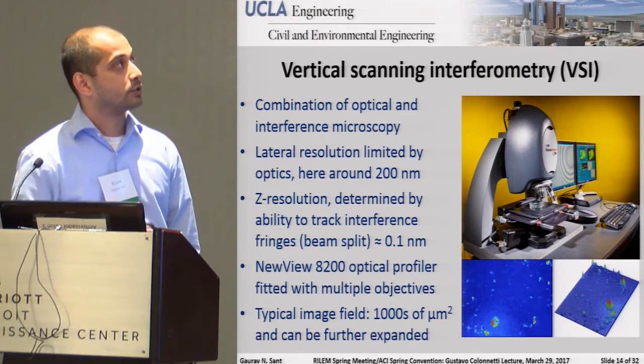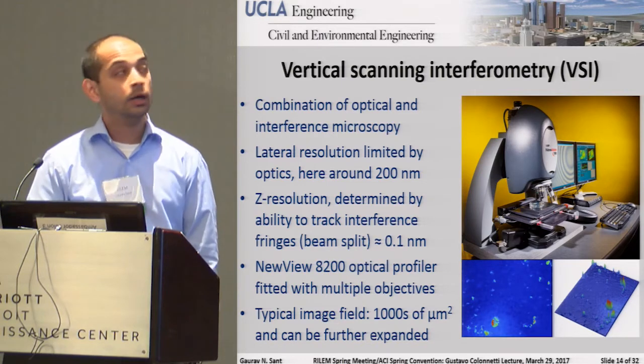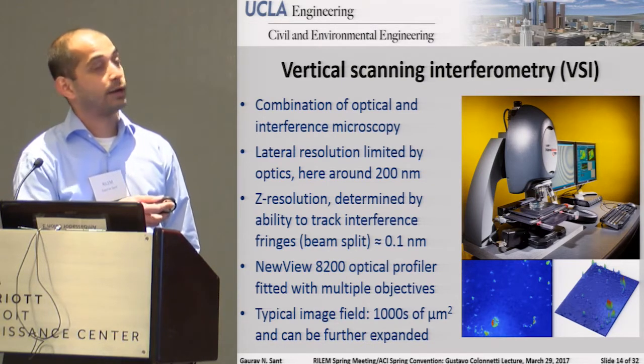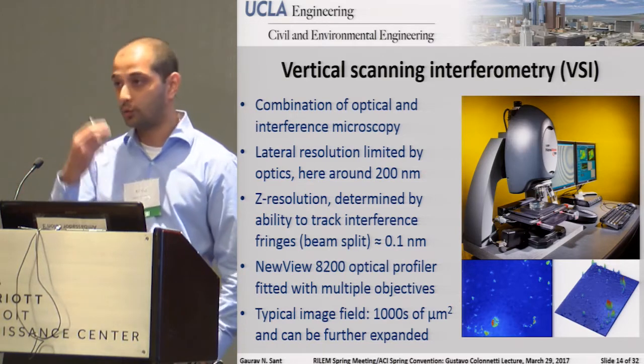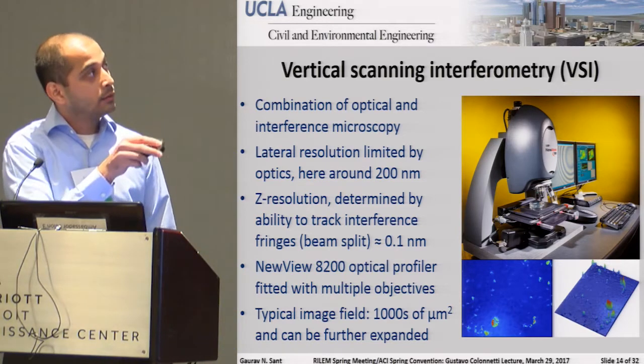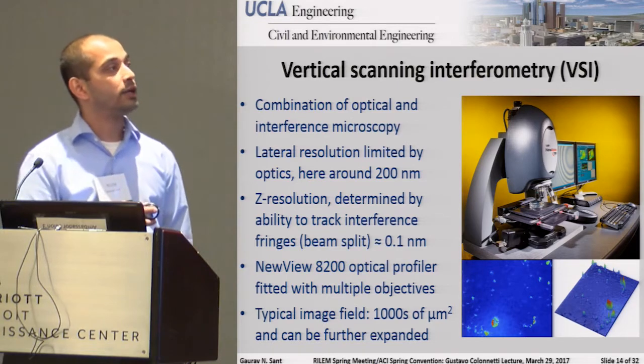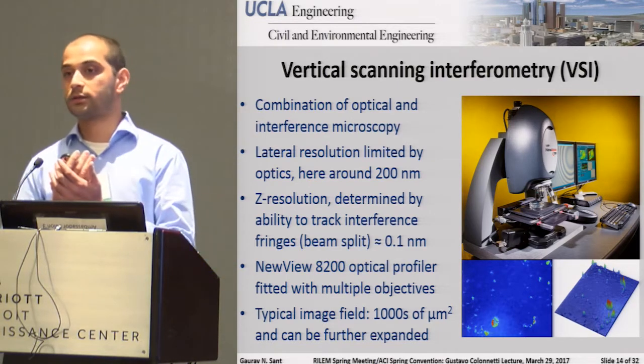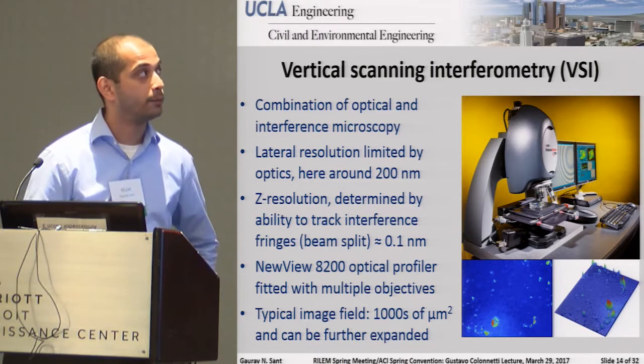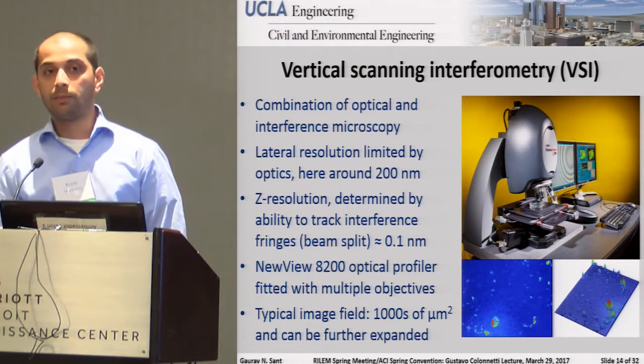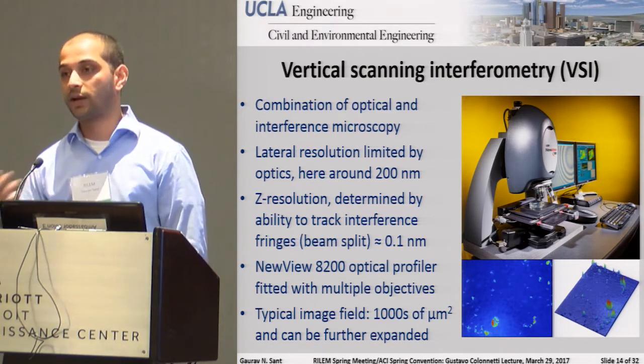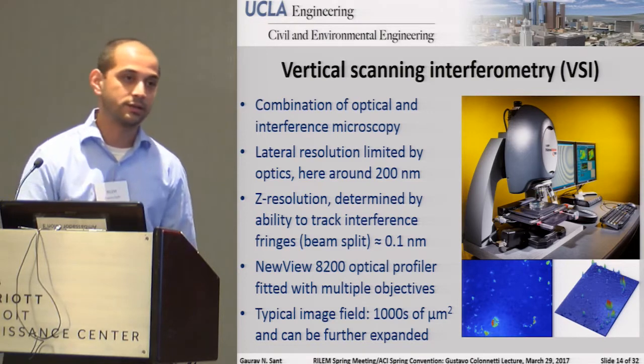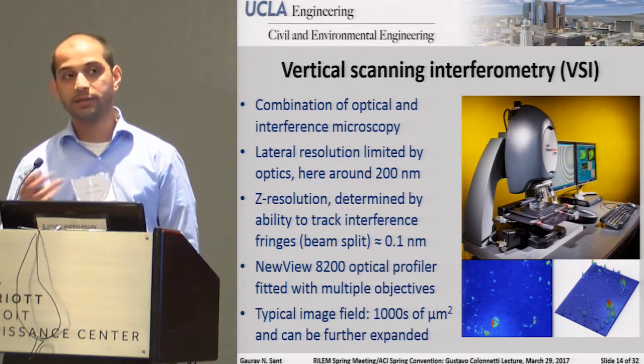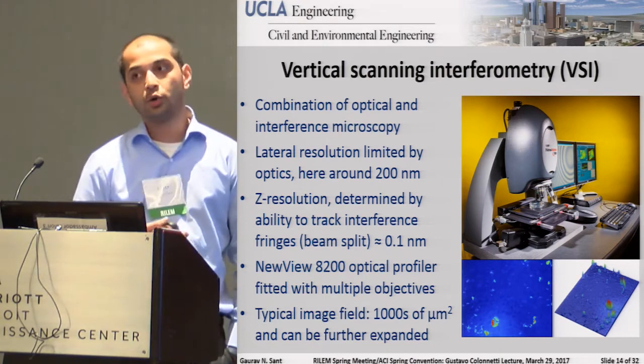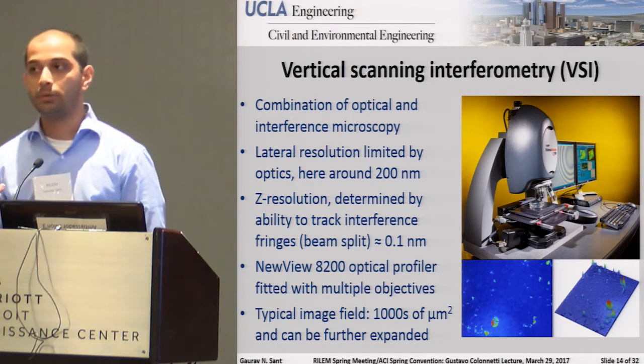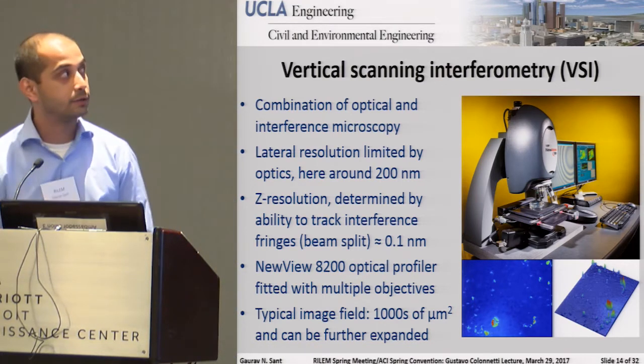So the idea of using vertical scanning interferometry is actually quite straightforward. It's a combination of what I will say is an optical microscope, so a typical microscope that you look at through an objective, and an interference microscope. So the idea of really trying to put these two things together, the optics with the interferometry, is actually quite straightforward. When you use a traditional optical microscope, you're limited by the diffraction limit of the optics. So essentially, this is described, for example, by the Rayleigh criteria or Abbe's diffraction limit. But long story short, it's very difficult to get resolutions which are better than about 100 to 200 nanometers.